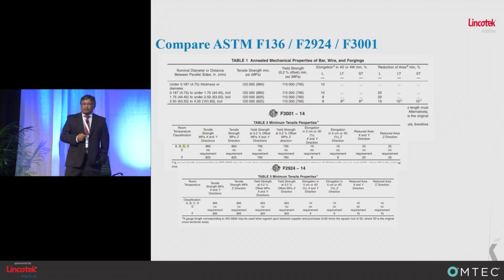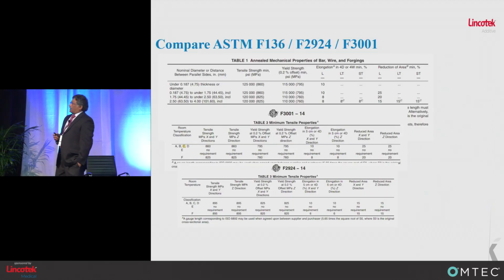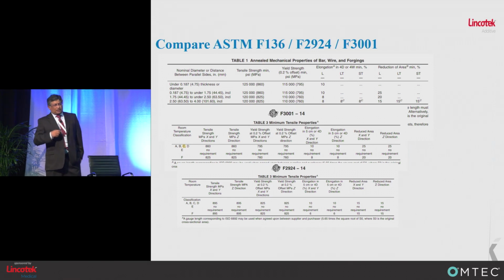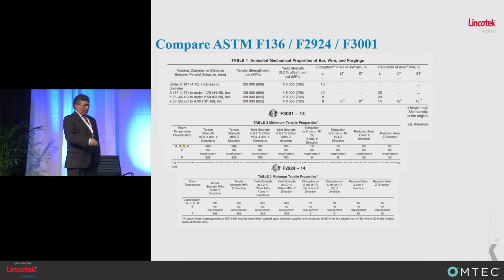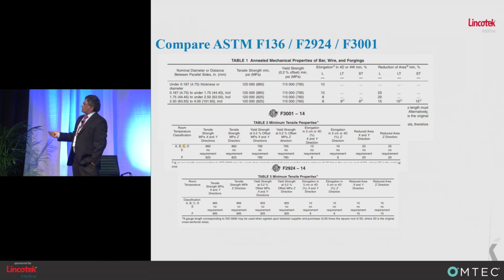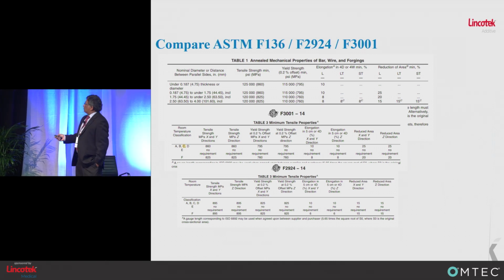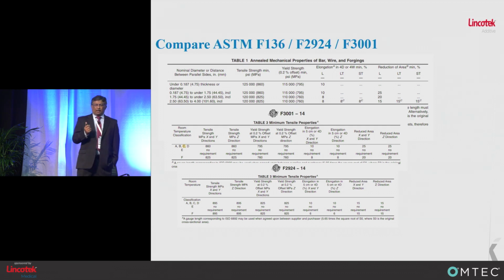So let's look at this. Like I said, the industry leaders, FDA, ASTM, we don't need to go through all this, but if you look at the ASTM standards around additive, we don't need to go through this line by line, but the first perception that mechanically additive parts are weak is absolutely incorrect. At least from a strength perspective, they're as strong as ASTM F136 parts, wrought titanium, right?